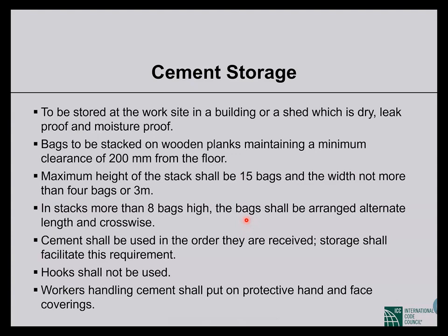But there is another restriction. If we want to stack more than 8 bags, then they have to be arranged lengthwise and crosswise. So if we put one bag in a north-south direction, the other bag on top of it should be in an east-west direction. So crosswise. Then we can make 15 bags stacked. Otherwise, if we put all the bags in the same alignment, then we can have 8 bags stacked at most.